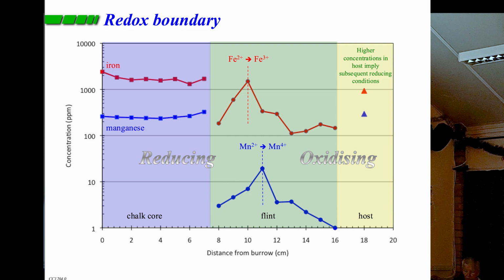Well, this is a cemented chalk core, iron and manganese concentrations. These are flint samples. And what you can see is iron, this top one, a great big peak, about 10 centimeters out from the core. Manganese, we get another peak a little bit further. So that means this flint, which is in green, was actually straddling the boundary between oxidizing and reducing conditions, rather like that.